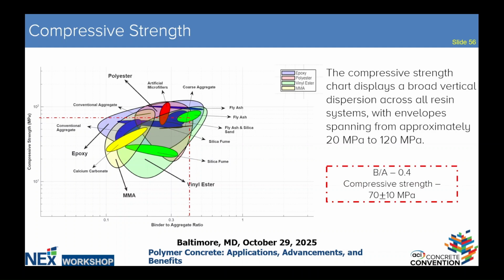So with this motivation from the Ashby chart, we've used MATLAB to get the compressive strength data for polymer concrete. Provided a builder wants to fabricate a polymer concrete with a binder to aggregate ratio of 0.4 and is interested in using a vinyl ester polymer resin with a subset data of, let's say, fly ash. So we have the fly ash here, which is a subset of the vinyl ester. The vinyl ester, as in the legend, is green, and the subset data for fly ash is also green, which is on the top right.